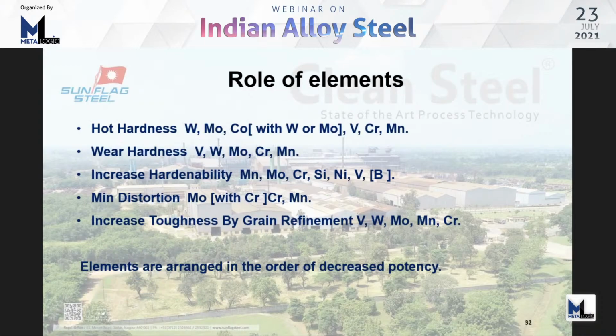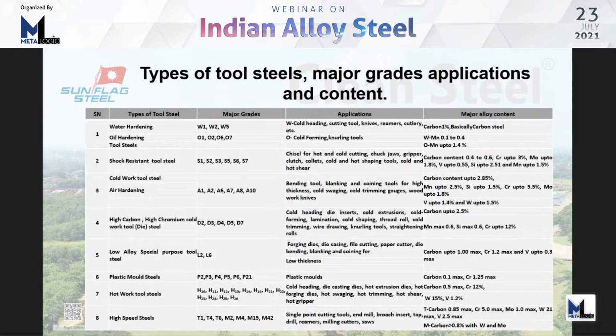The role of elements: the hot hardness is imparted by tungsten, moly, cobalt, vanadium, chromium, manganese. Wear hardness by vanadium, tungsten, moly, chromium, manganese. Hardenability by manganese, moly, chromium, silicon, nickel, vanadium. Minimum distortion by moly with chromium and manganese, and toughness by vanadium, tungsten, moly, manganese, and chromium. This is a table which indicates the types of tool steels with major grade therein, with applications and major alloying elements. I will not read this because of paucity of time.